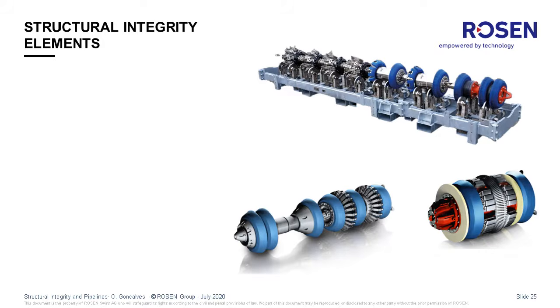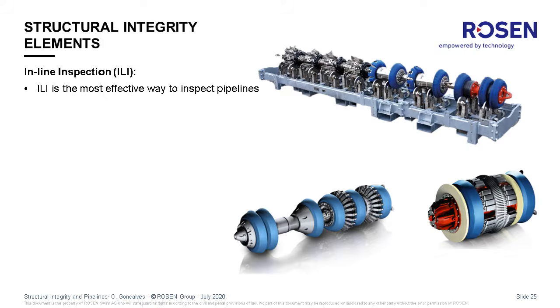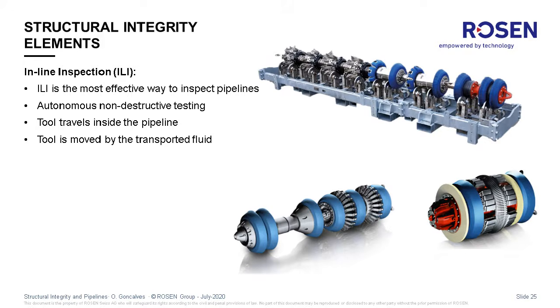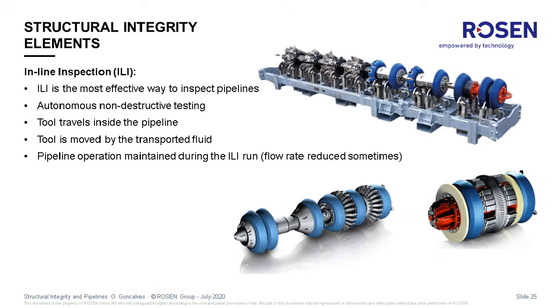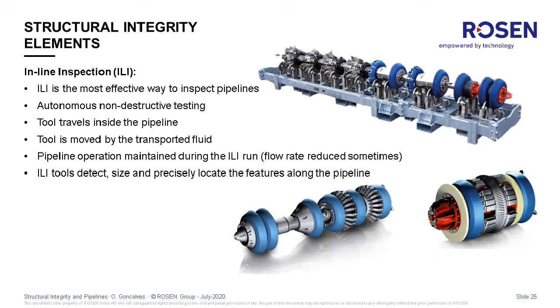But fortunately, we do have something else, which is inline inspection. Inline inspection is a technology which has been around for some time. It's the most effective way to inspect pipelines. It's basically an autonomous, fully automatic, non-destructive testing. The tool travels inside the pipeline. It's moved by the transported fluid. There is no disruption for the pipeline operation. Sometimes it's necessary to reduce the flow rate in order to avoid overspeed of the tool, which might compromise the inspection quality. But in most cases, even that is not necessary.